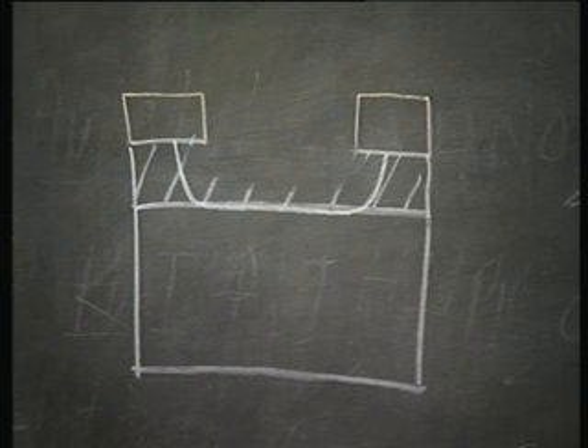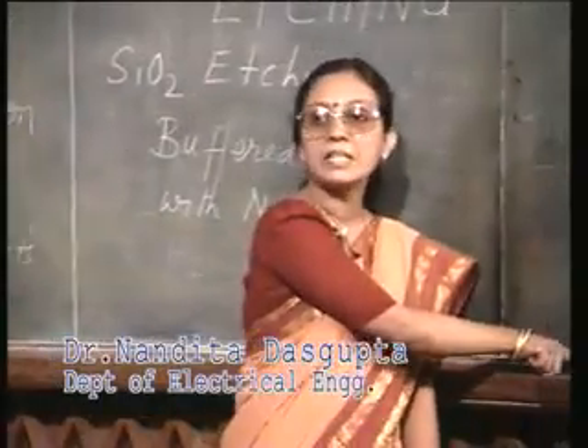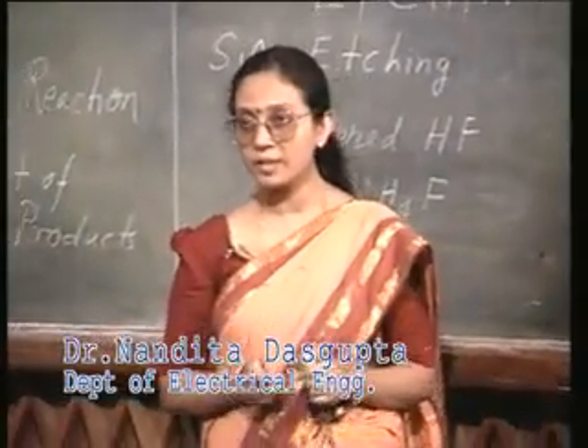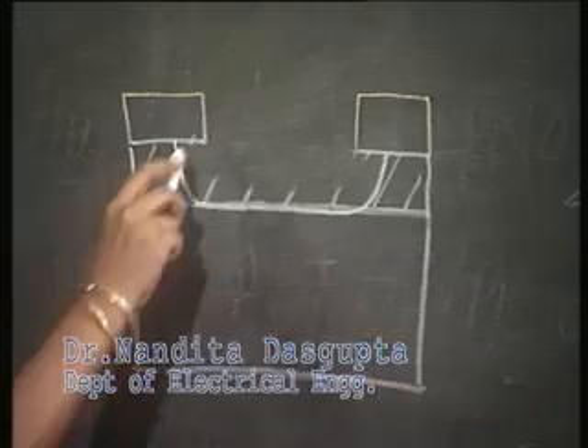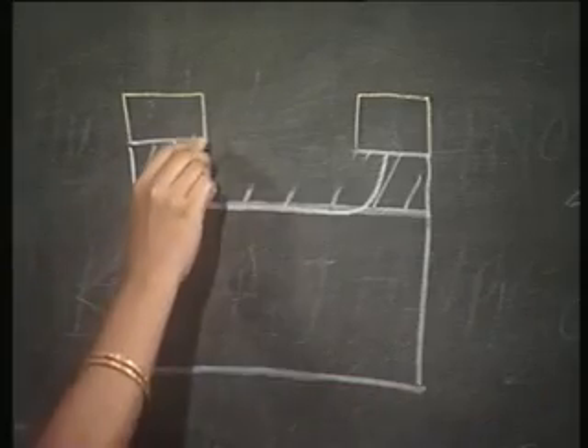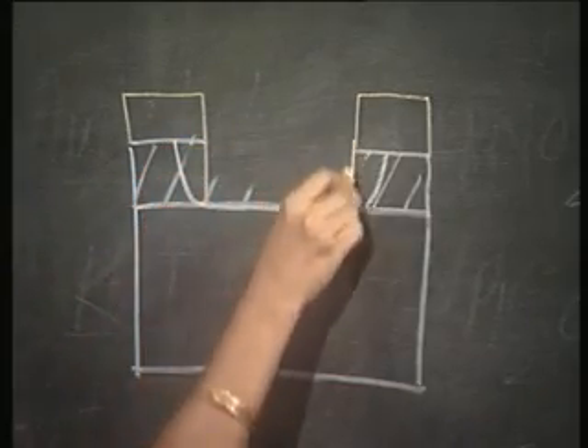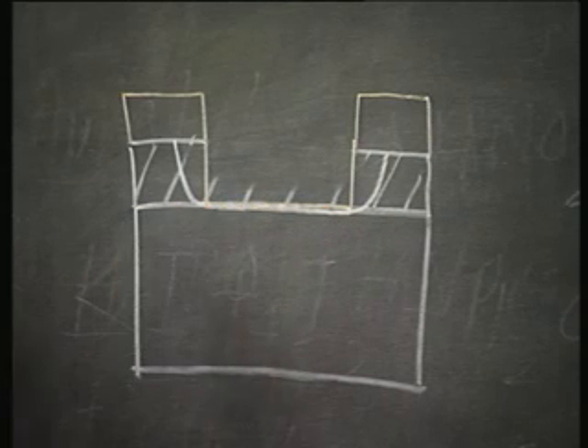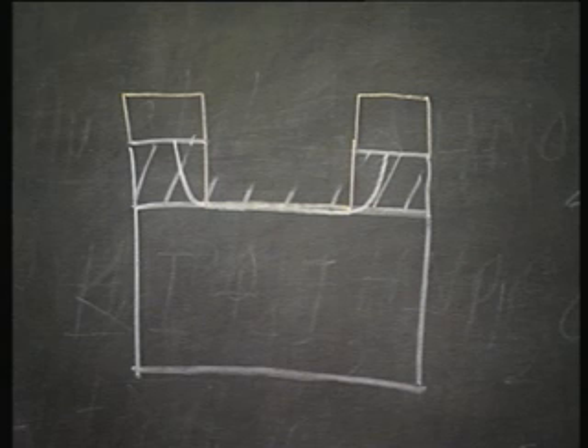I have what is called an undercut under the mask. Ideally, my etching profile should have been like this, but since the etchant cannot distinguish between the side wall and the bottom surface, it has gone under the mask on both the sides and I have a profile like this.